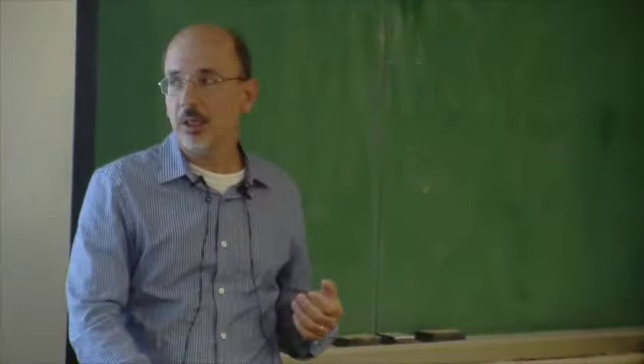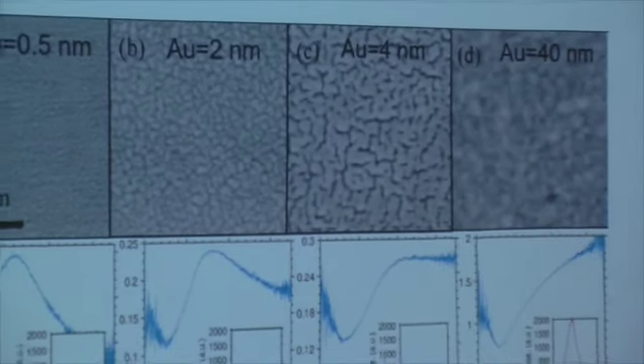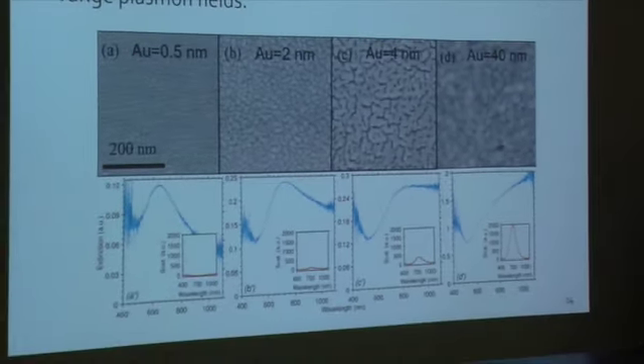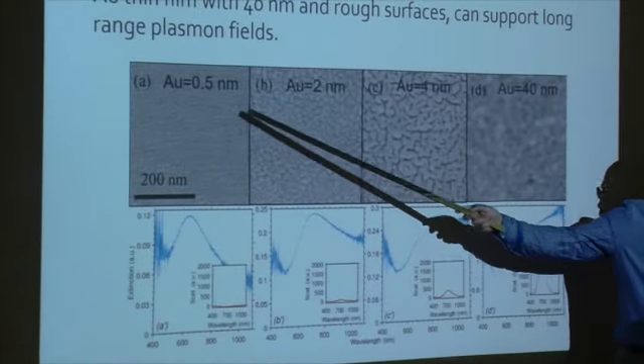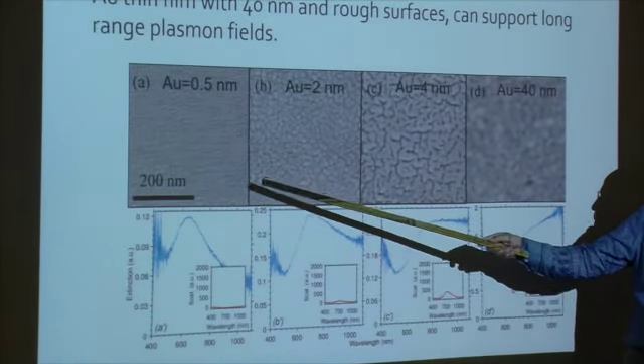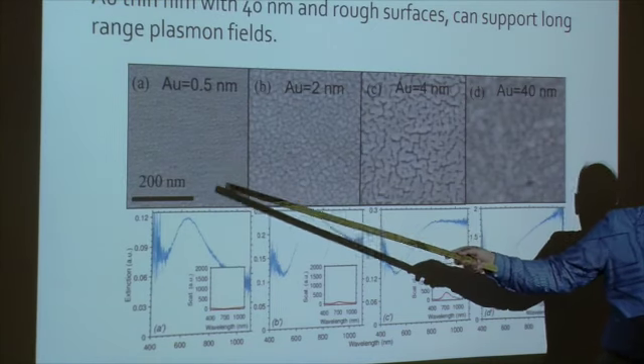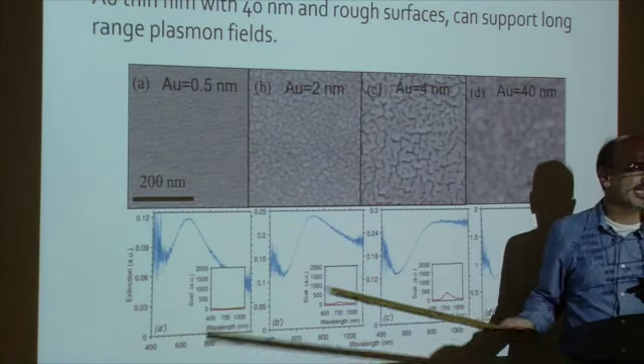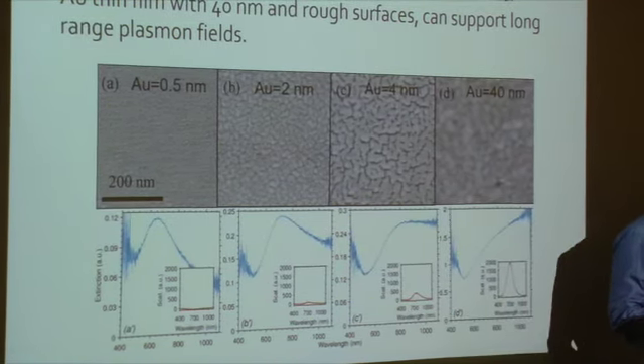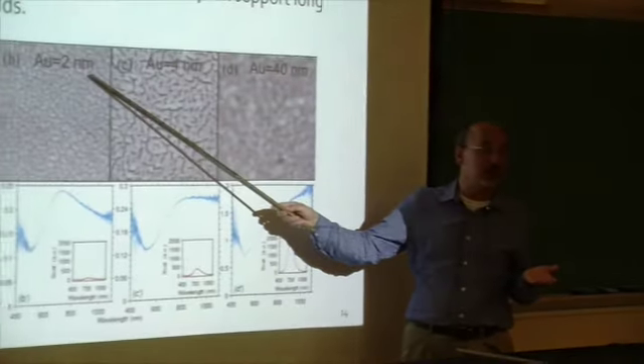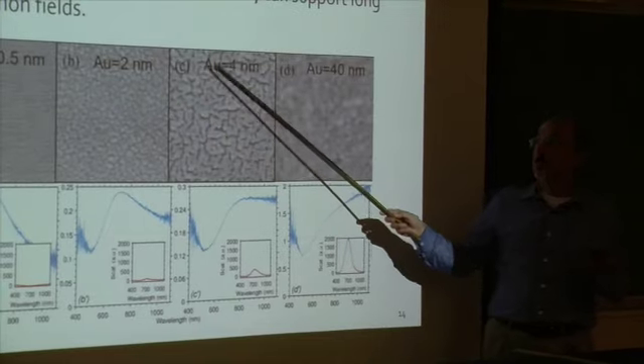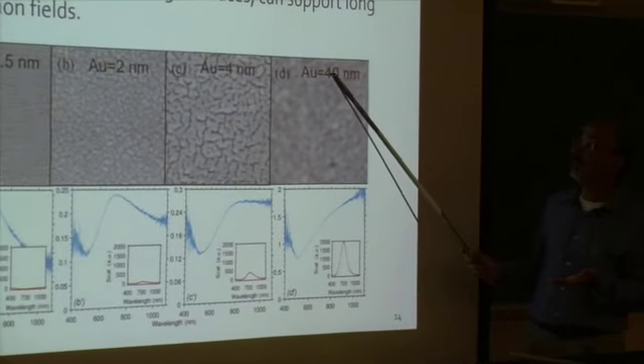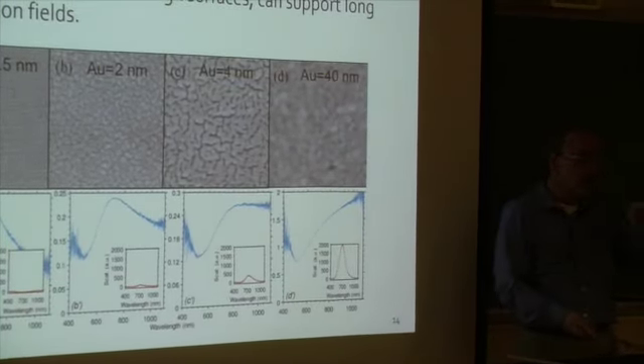Here I show the SEM images of different thicknesses of gold on silicon. You can see that if it is 0.5 nanometer, you see some little islands. This scale is 200 nanometer. They are tiny islands packed together. But with 2 nanometer, it becomes like this. 4 nanometer is this, and this is 40 nanometer, which is the thicker substrate that we have.